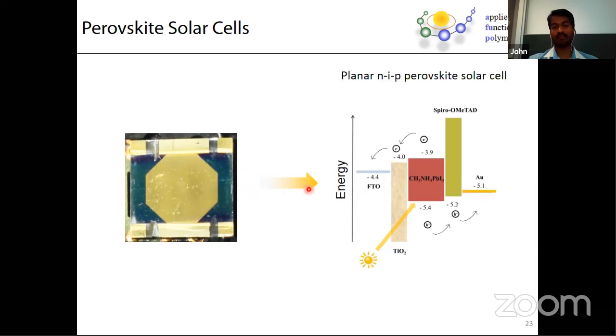If you look closely from the energetic point of view and also at the materials involved in such devices, we call this an NIP perovskite solar cell. NIP means you have N-type material on one side. Here we have titania as the N-type material, and perovskite, methylammonium lead iodide, which is basically an intrinsic semiconductor. And then you have a P-type material at the other end of the system, where we have spiro-OMeTAD as a hole conducting material, or let's say P-type material. And then these layers are sandwiched between FTO and gold.